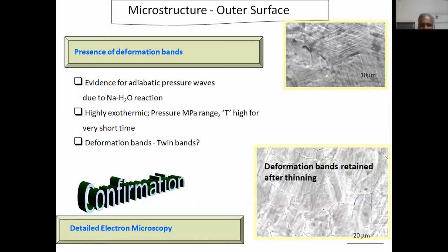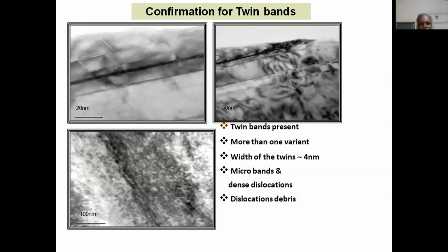So to see whether the deformation bands are due to twinning also, a detailed electron microscopy was done. You could see the parallel bamboo-like twin bands beautifully seen at the edges. This is the edge. You could see that deformation bands are nothing but twinning bands. So that means twinning has dominated extensively because of the high temperature and pressure generated by the sodium-steam interaction. We look at the right side as well as beneath, the debris of dislocations. The kind of dislocation which I showed earlier as an example is quite different from this. This debris is very severely interlocked, and therefore this dense dislocation formation suggests that the reaction rate, the deformation rate, is very fast.